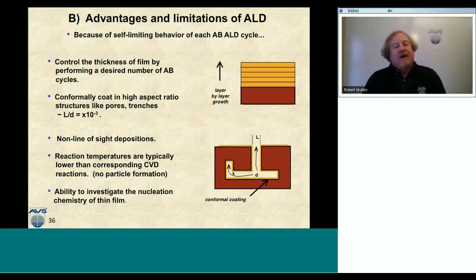Now, the other advantage is that the reaction temperatures of ALD chemistries are typically lower than their corresponding CVD reactions. And this is both good and bad. It's good in the sense that we can coat materials at lower temperatures, so that opens up the space of coating polymers or other materials that are sensitive to temperature.